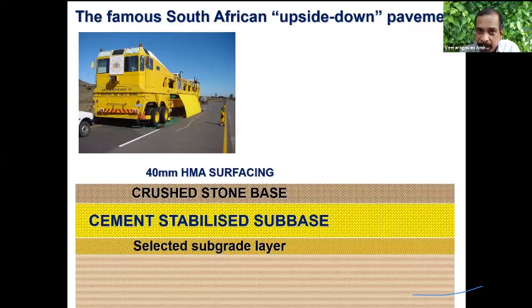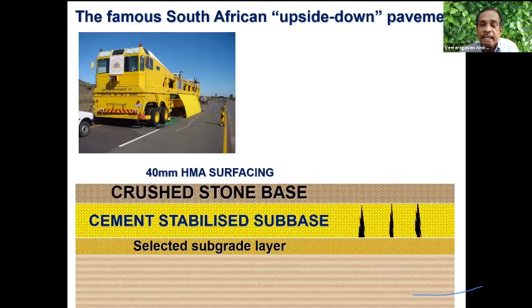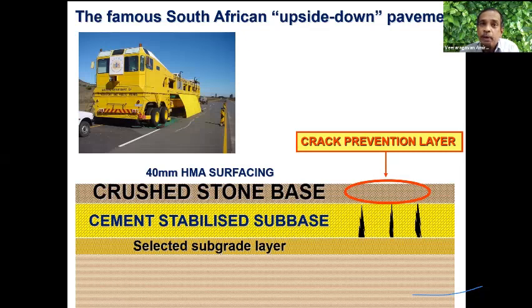What is to be done? I can prevent these cracks from reflecting on the top. I can have a crushed stone base as a cushioning layer above, which will prevent the crack from propagating to the bituminous layer. That is called a crack relief layer. So as a civil engineer, you may do a PhD on a cement treated base, but you should know how to use it in a pavement system. What are the implications? What are the causes, pros and cons? Definitely it will crack. You should take precautions when you do this.